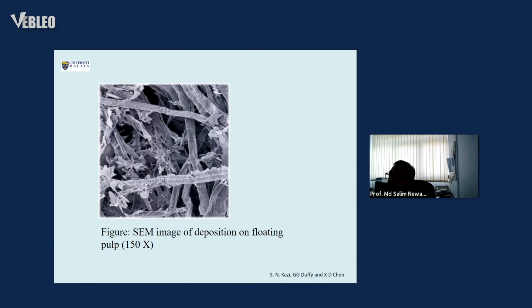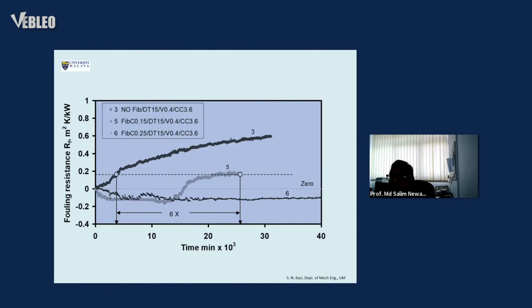And these eddies affect the boundary layer of the heat exchanger surface, and they retard the deposition on the heat exchanger surface. So with this understanding, if we consider the induction time here, it not only increases, but with the increase of concentration, it remains a longer time without any deposition.